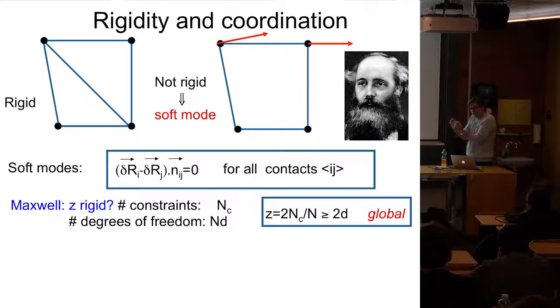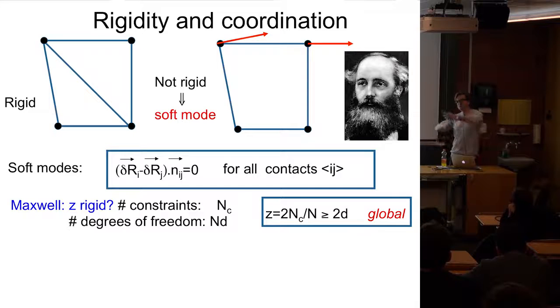As you unjam those packings, they approach this critical value for the coordination. If you go to even lower coordination, which is what happened in this movie, where you're not coordinated enough, then you have zero modes, then you have floppy modes. Actually in the movie of the suspension I showed you, the displacement is along floppy modes. So the point is that floppy modes appear when the coordination is below some threshold. I think it's very intuitive, and I would not derive it, that if the coordination is above, you will have a reminiscence of the proximity to this threshold in the spectrum of modes. Okay, so coordination certainly matters.